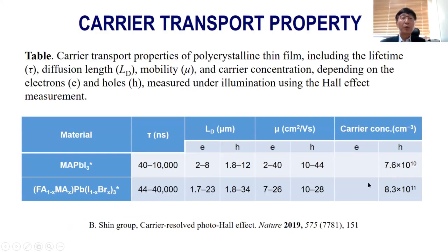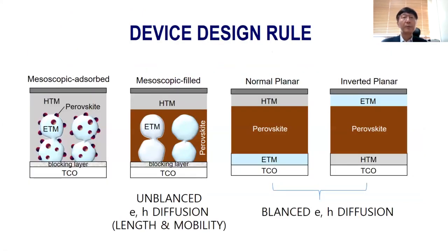The carrier transport property was recently measured by the photo Hall effect measurement, and it was found that the MAPbI3 or the FA mixed phase polycrystalline film shows a micrometer scale diffusion length. And interestingly, electron and hole transport is almost balanced. Therefore, it is very good for designing the perovskite solar cell structure. So the device design rule is here.